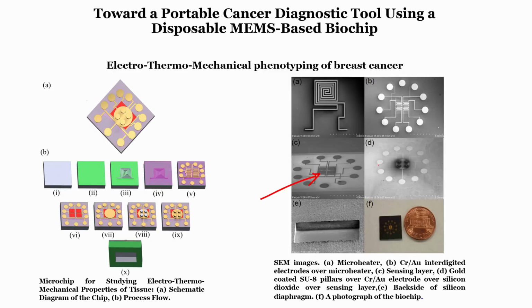Our next step is to have a gold pad, right, which is in the center, okay, this one gold pad, and on that gold pad we require SU8 pillars. So, can I deposit the gold directly on piezoresistive material? This is piezoresistive material, right. These 4 black squares or gray squares in the center are piezoresistive materials. But can I deposit a gold, which is a metal, on piezoresistive material? It will get short, right.